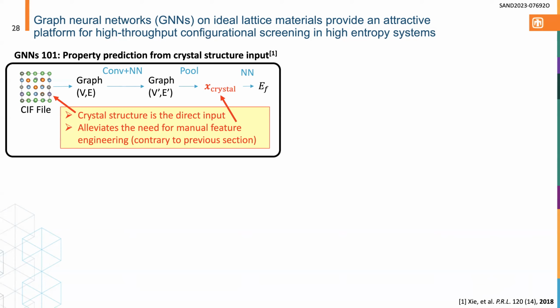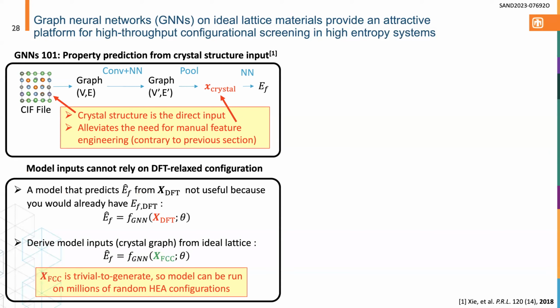If you pool all the information, aka you add it or you average it, or you do a max operation, then you can derive this feature vector, which now describes the entire crystal, and you can use that to predict something like the formation energy. So that's exactly what was done in Xie's first papers predicting formation energies. So the issue, though, if you want to do thermodynamic sampling and predict phase stability of these alloys, you of course can't be using the DFT relaxed crystal structure.